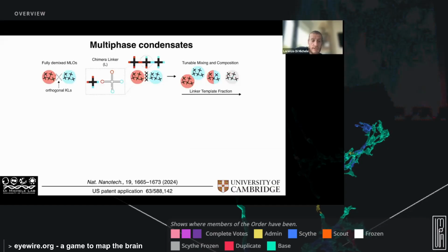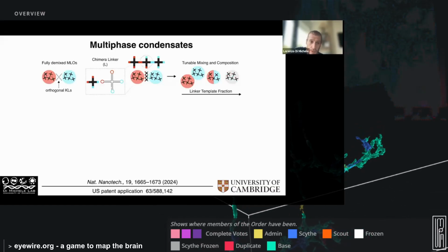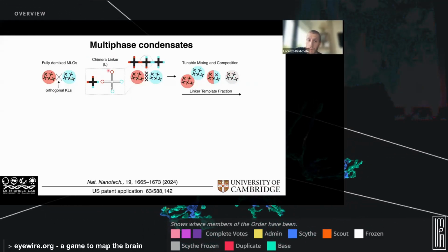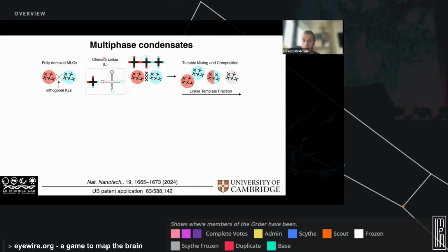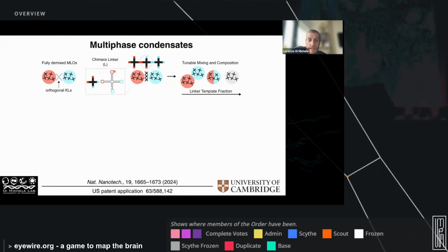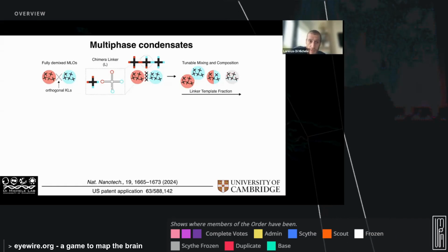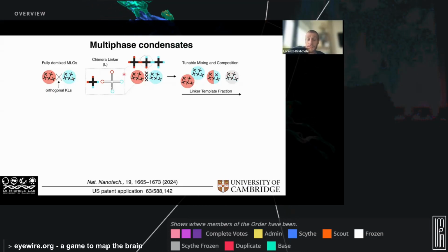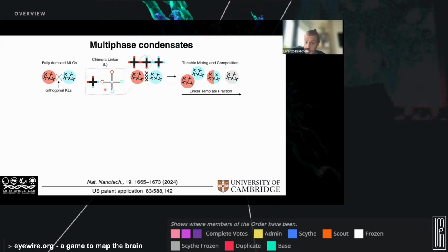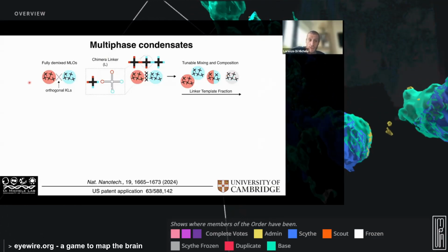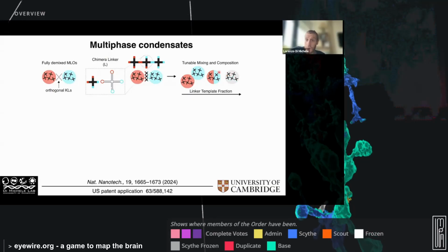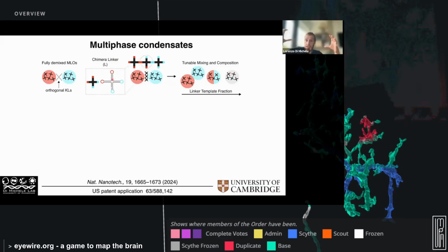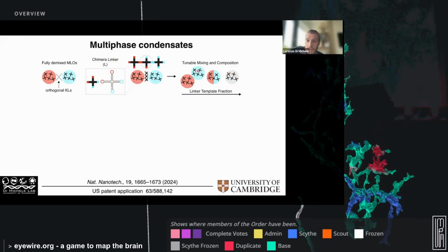A good place to start is from our non-miscible condensates A and B that you can see here, and then introduce a third component that we call a chimera or linker nanostar that now has 2 kissing loops that are red, so they bind to A, and 2 kissing loops that are cyan, therefore they bind to B. And the idea is that the more of this you express, the more you go from a situation in which A and B are demixed towards a situation in which A and B are fully mixed, because these linkers basically help the A and B phases mix together.